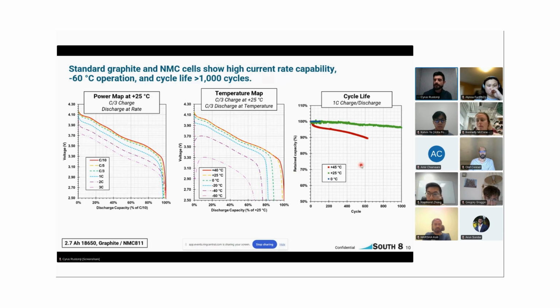For cycle life, these cells have been charging and discharging at 1C. And this plot needs an updating. I think this is actually outdated data. But anyway, we can go well past 1,000 or 2,000 cycles at room temperature, no problem at all. At higher temperatures, we are projected to hit about 1,000 cycles, so pretty good up to 45 degrees Celsius. And then at 0 degrees, this is pretty typical for lithium-ion cells. They cycle pretty nice at 0 degrees as well, but it's pretty early in testing for us there, and so we'll update this data hopefully soon.